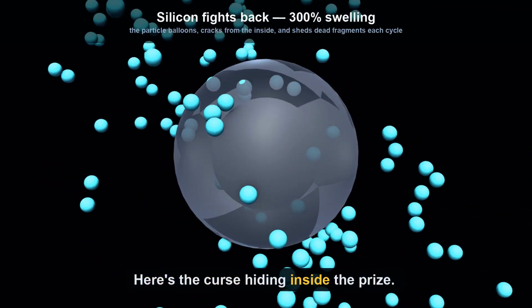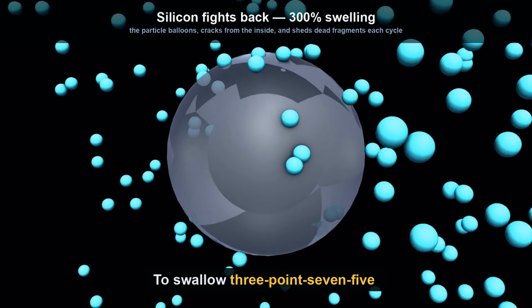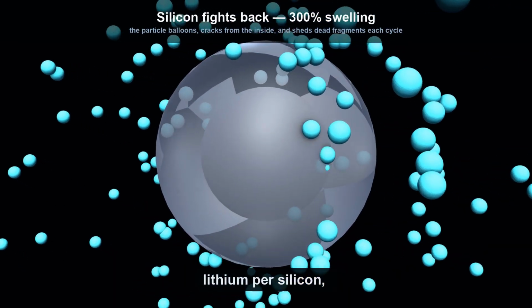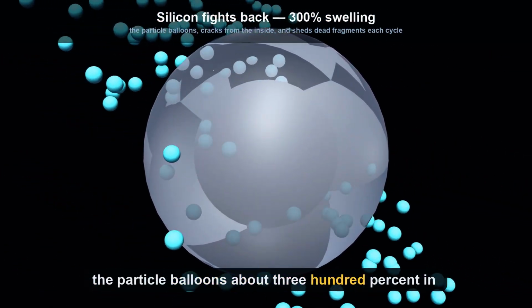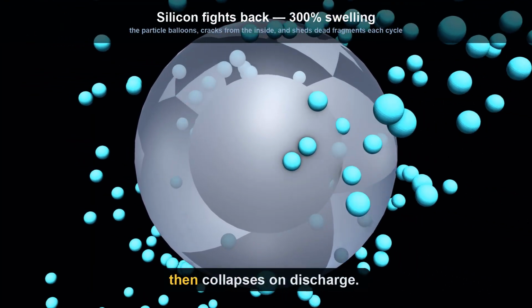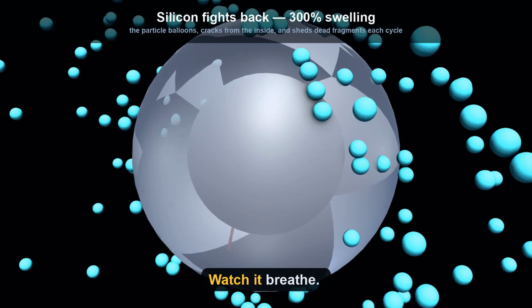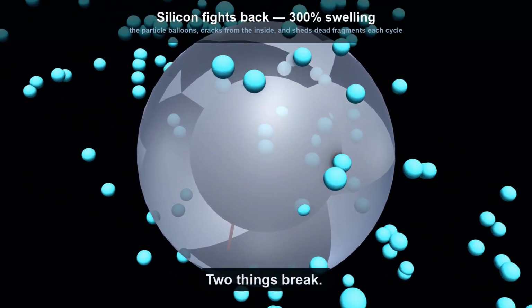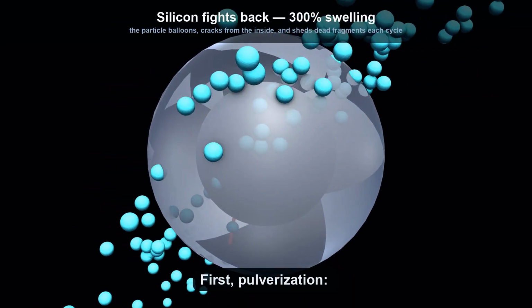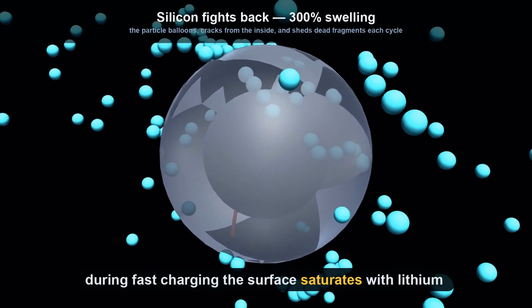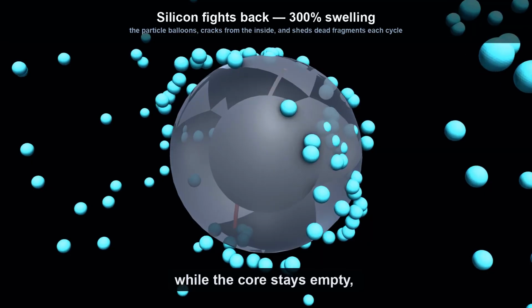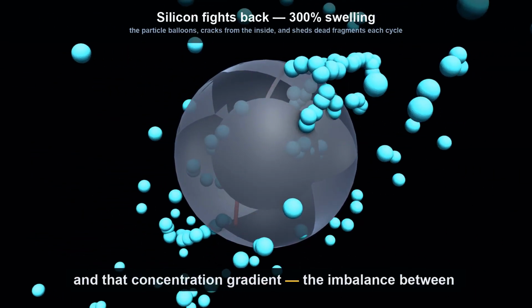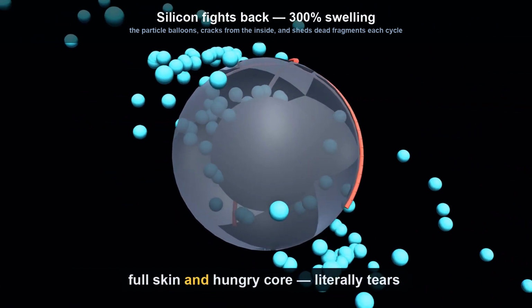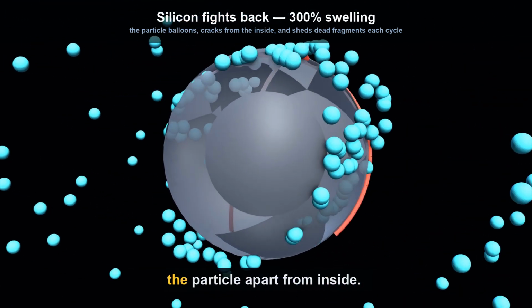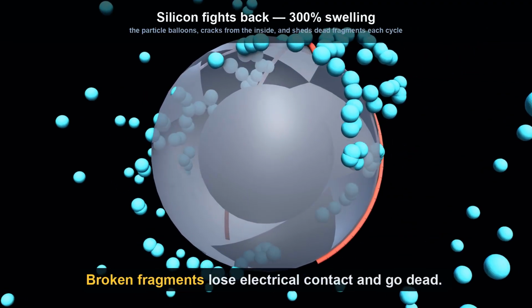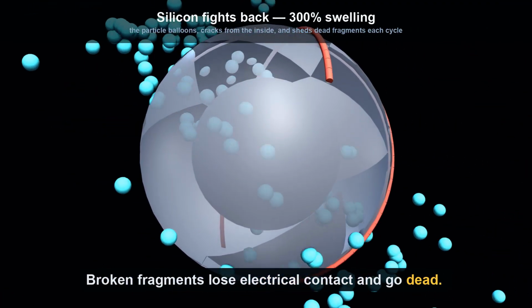Here's the curse hiding inside the prize. To swallow 3.75 lithium per silicon, the particle balloons about 300% in volume on charge, then collapses on discharge. Watch it breathe. 2 things break. First, pulverization. During fast charging, the surface saturates with lithium while the core stays empty, and that concentration gradient, the imbalance between full skin and hungry core, literally tears the particle apart from inside. Broken fragments lose electrical contact and go dead.